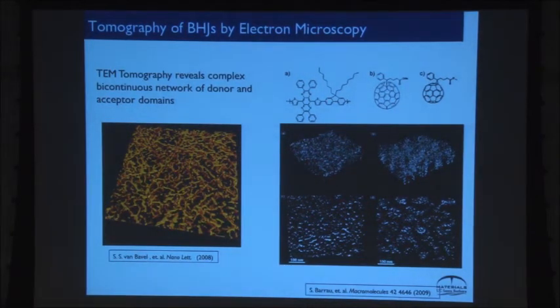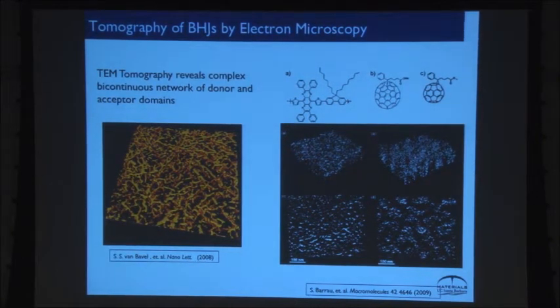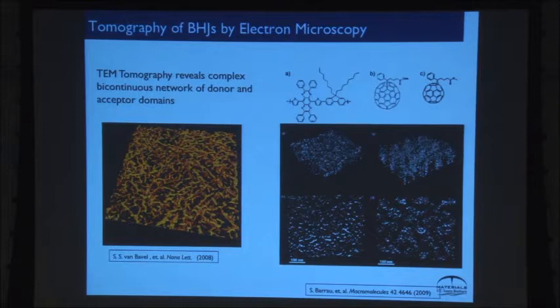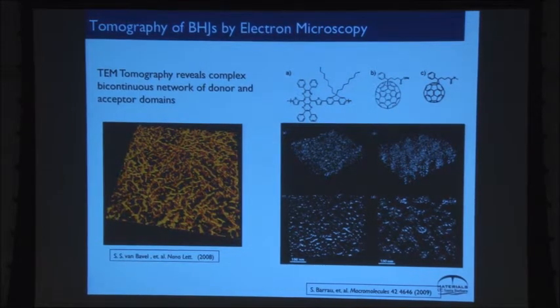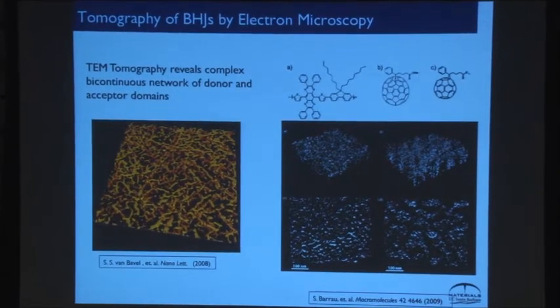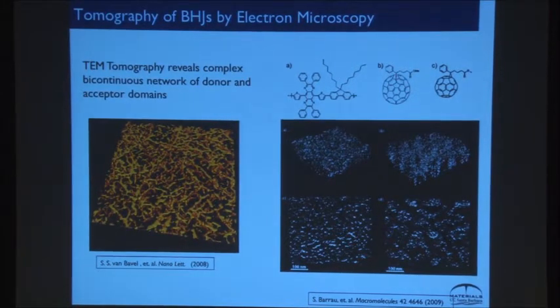What do these things look like? I said they're nanoscale phase separated. If you take a solar cell like this, spin coat it, put it in a TEM and do something called TEM tomography, where you try to look at the electron density contrast between the two phases, you see images like this. And typically people will just show one phase. We don't know that this contrast is perfectly due to pure domains of one material or the other. We just know there's a lot more electron density here than in the black parts.